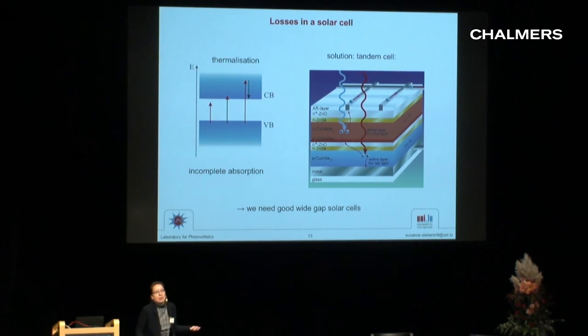A single solar cell never makes perfect use of the solar spectrum. One solution, you just heard from Joseph: we shift the energy of the solar spectrum to the range where the solar cell works optimally. Another solution is a tandem solar cell, where we put two solar cells on top of each other, and one uses the blue photons, the high energy photons, more efficiently, and the second one uses the low energy photons more efficiently. And by putting those two together, we can go to higher efficiency.